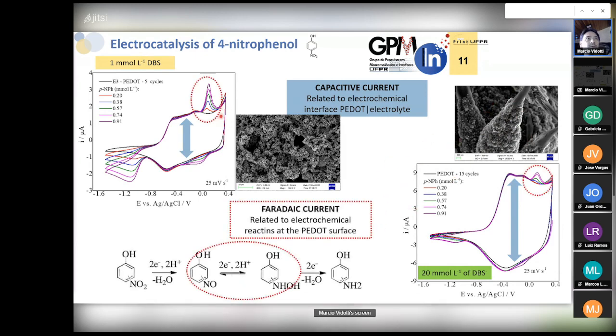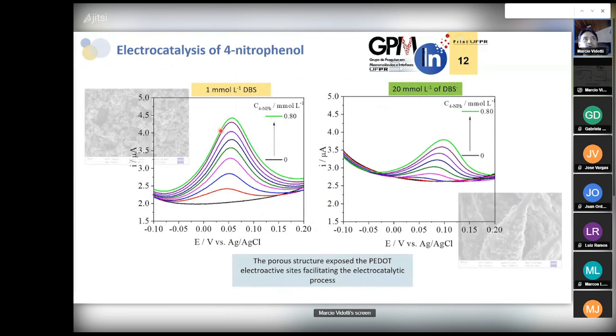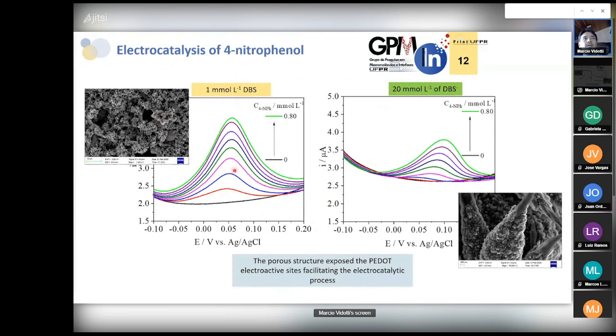But on the other hand, when we observed the electrocatalytic response towards the oxidation and reduction of 4-nitrophenol, we observe that the response is a little bit different. And if we look in more detail, we observe that the use of the 1 millimolar DBS, due to this porous structure, is somehow more electrocatalytic compared to the structure formed in the presence of the template structure. We're not quite sure yet why this happened, because we are studying this kind of behavior right now using other techniques. Somehow the electrocatalytic active sites are more available for the oxidation of 4-nitrophenol to aminophenol compared with these modified electrodes.